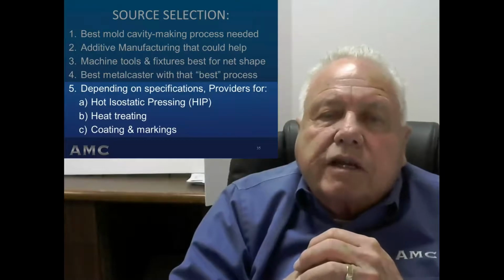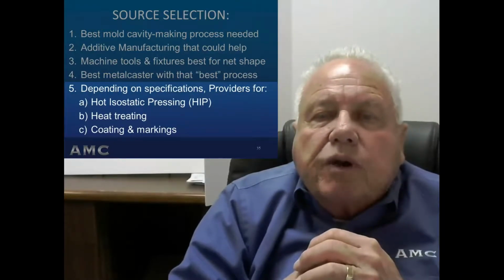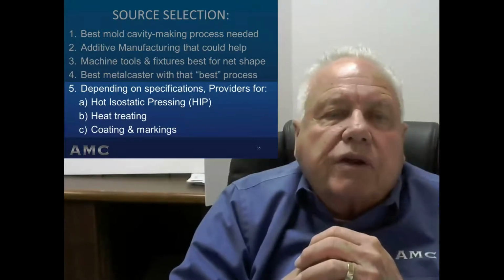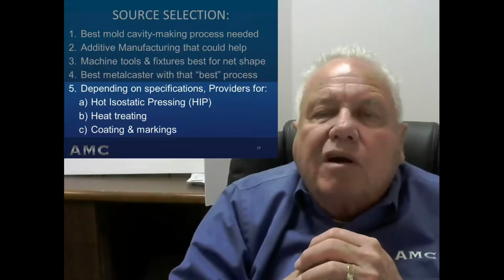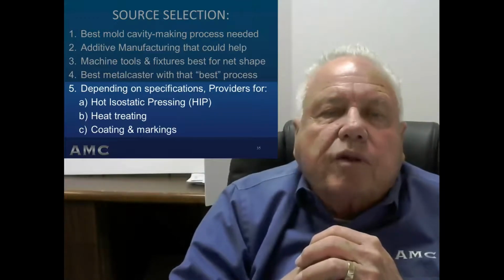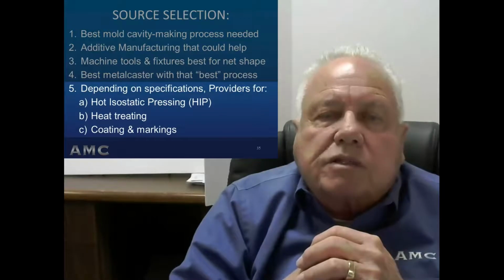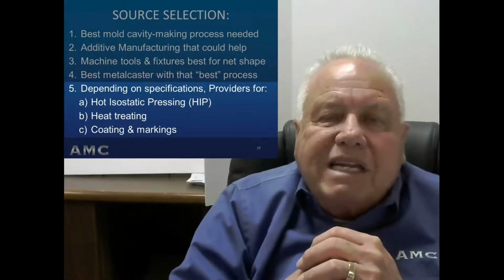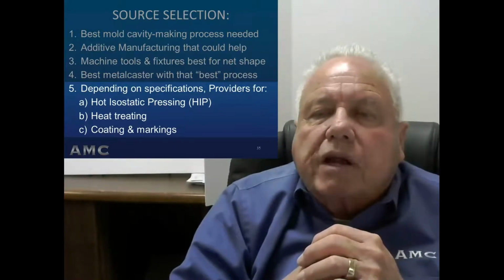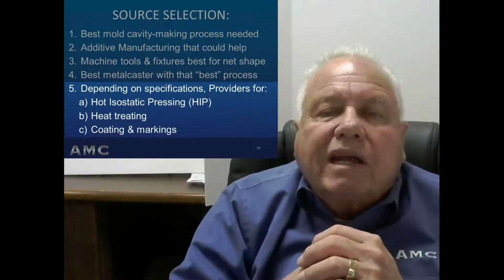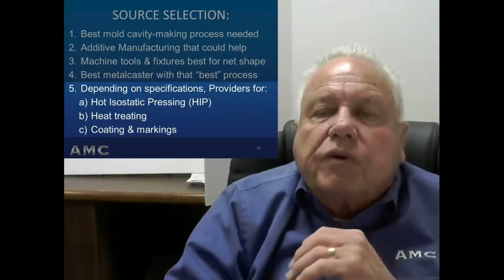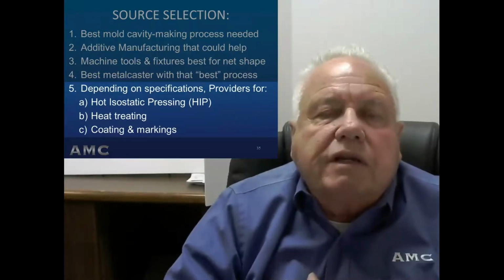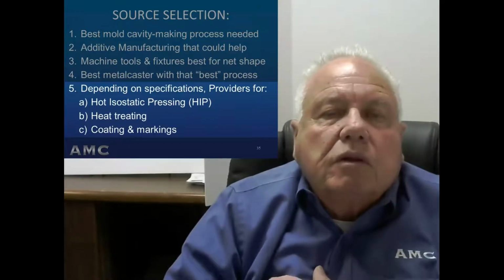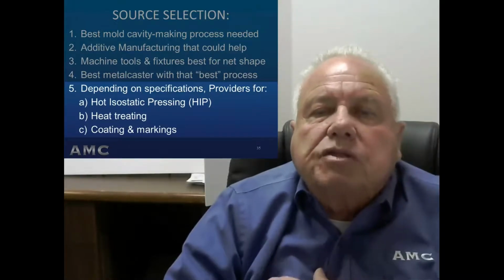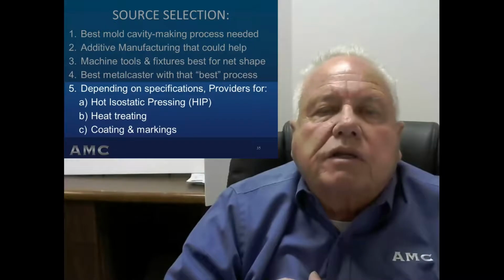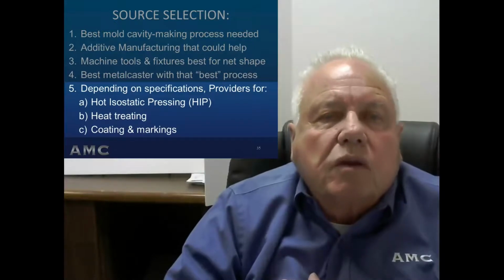Selecting a hot isostatic press, or hipping press, provider if the solidification integrity and dynamic property requirements are very high, beyond the capability of the chosen mold cavity making process. The best heat treater based on the chemistry and microstructure of the chosen alloy and the probability of fixturing for heat treat and or fixturing for straightening afterwards. The coater based on the chemistry and processes of any specified coating, including markings.